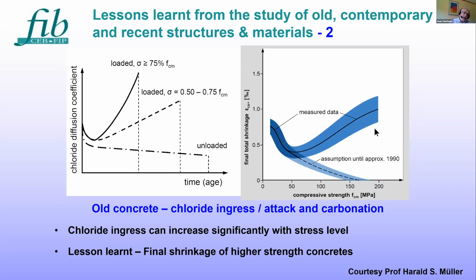Continuing in this theme, on the left-hand graphic, you've got chloride diffusion coefficient on the vertical axis and time on the horizontal axis. But again, the influence of load history and past behavior of the structure is brought out by those curves indicating that chloride diffusion can be significantly higher in a highly stressed structure than in an unloaded structure.